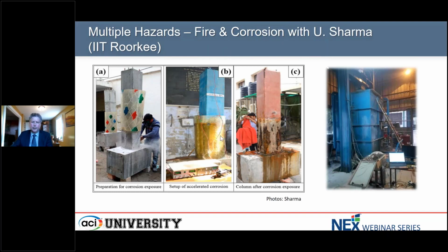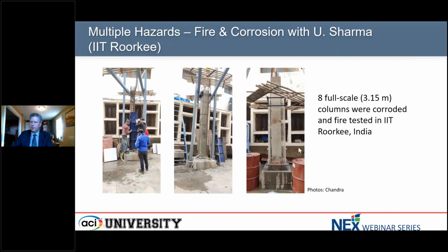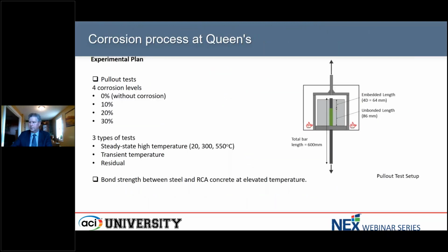We've also been doing work looking at fire and corrosion, and this work is with colleagues in India, Professor Sharma at Indian Institute of Technology in Roorkee. We're looking at these fairly large columns that have been corroded over time. You can see the results, and then they're actually tested for their performance in fire. And we did see some effects of the corrosion, but not huge amounts of reduction in the fire resistance. So we're looking to understand it a little bit more in material tests that we've been doing at Queen's University, and really looking at pullout and trying to understand the bond performance at high temperature when we have that.